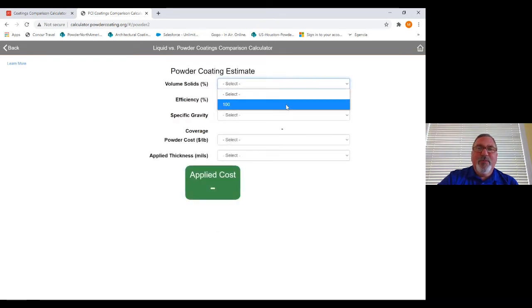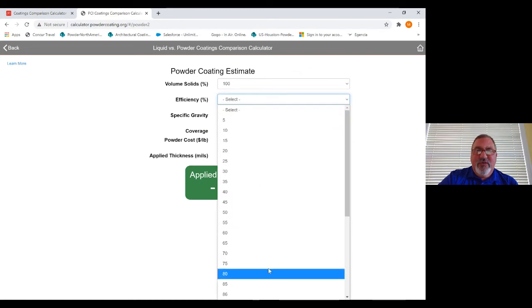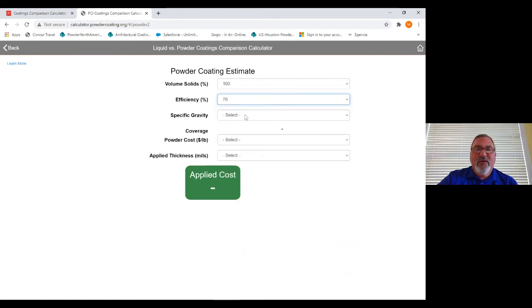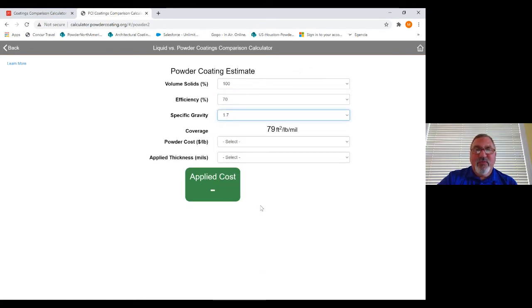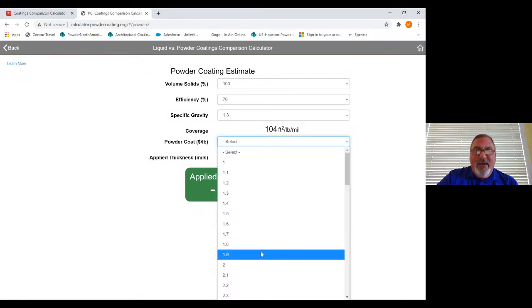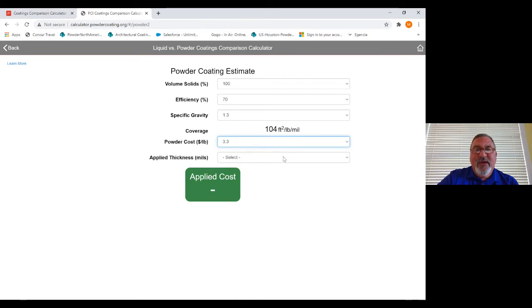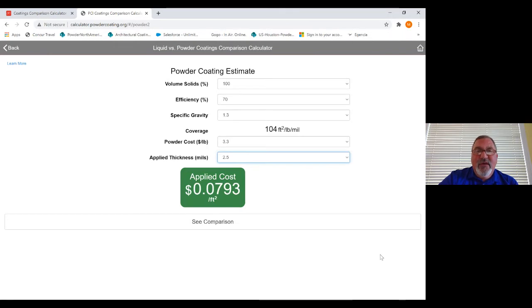So again, we're 100%. Efficiency still 70. Specific gravity on this, oops, hit too quickly, is 1.3. Now you can already see the lower specific gravity gave us more square feet per mil per pound. And in this case, the cost was higher, $3.30, and the film thickness is the same at 2.5 mils. And so now you can see this is 7.93.